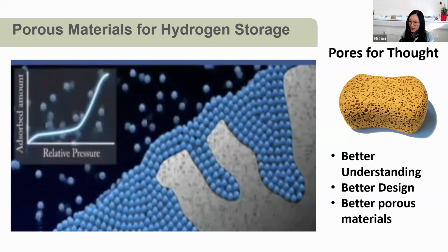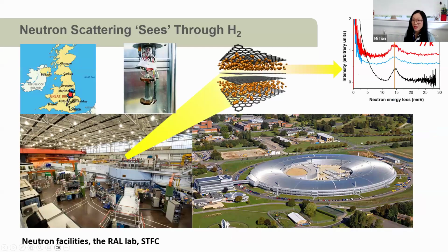So my job is to gain a better understanding of how hydrogen molecules interact with the surface, therefore leading to a better design for porous materials. One of the challenges in my research is how to characterize hydrogen. As mentioned, hydrogen is a lightweight gas, is invisible, and is insensitive to lab-based techniques, for example X-ray diffraction. Therefore, we found neutrons are the best candidate for this job. A neutron is highly sensitive to hydrogen. A neutron beam can deeply penetrate everything, the cryostat, the high pressure sample container, the sample itself, and directly probe gas molecules inside the pores.